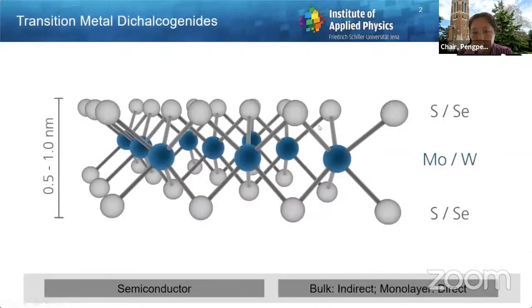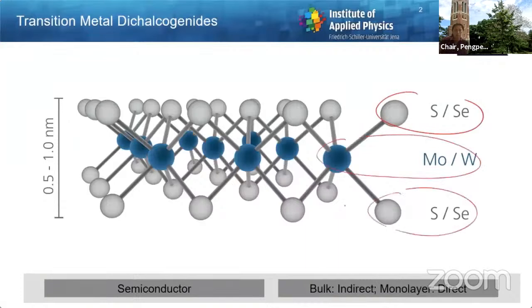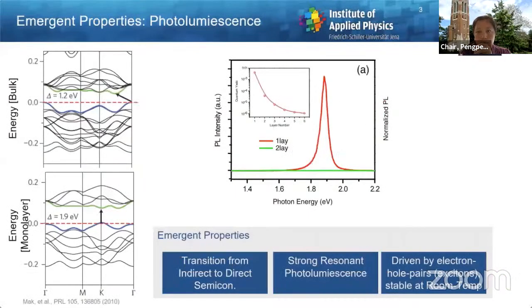So the material in question for today is transition metal dichalcogenides. It's somewhat similar to graphene in the sense that it forms monolayer crystals, with the difference that this monolayer crystal is not a single layer of atoms, but it consists of unit cells of three atoms, namely a chalcogen layer on the top, a transition metal layer in the center, and a chalcogen layer at the bottom. And these materials are very interesting for optics and photonics because they are semiconductors, with the particular quirk that if you transition from the bulk, so from the multi-layer system to the monolayer system, they transition from an indirect to direct band gap, as you can see on the left-hand side on this screen